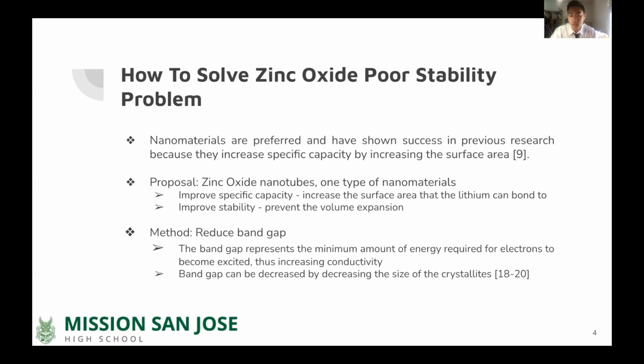In our study, density functional theory is used to calculate the band structure and density of states of zinc oxide nanotubes. The anode with zinc oxide nanotubes is fabricated to test the results of the simulation and compare them to the cyclic performance of traditional bulk zinc oxide. The zinc oxide nanotubes were fabricated with hydrothermal reactions and exhibited excellent performance and cyclic stability, which should be used as a reference for future studies.